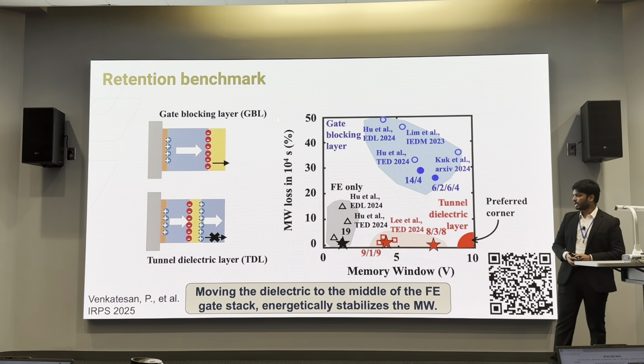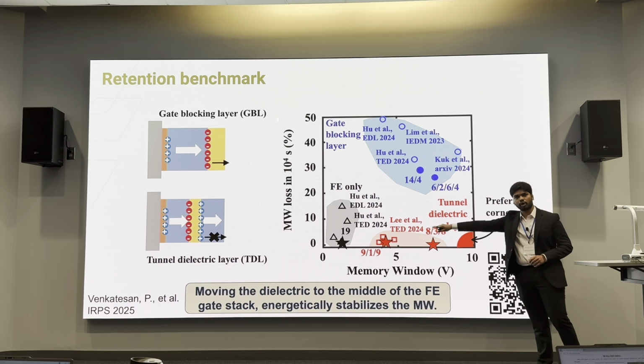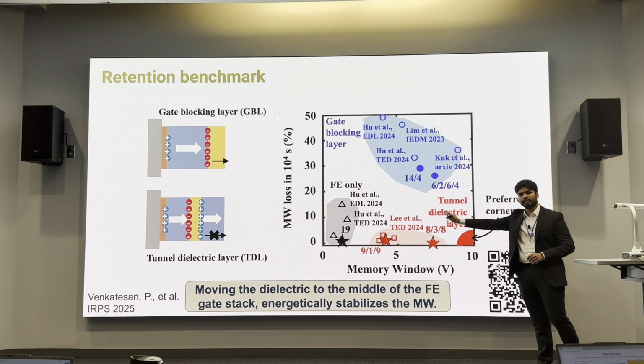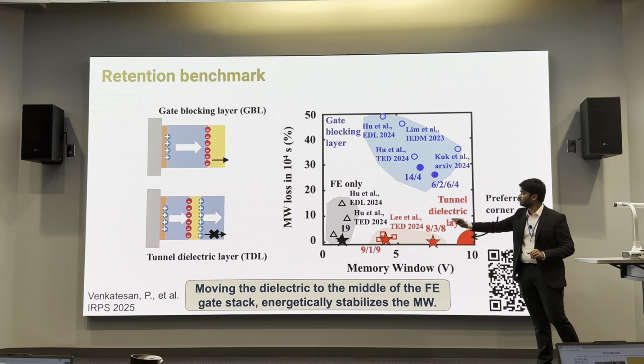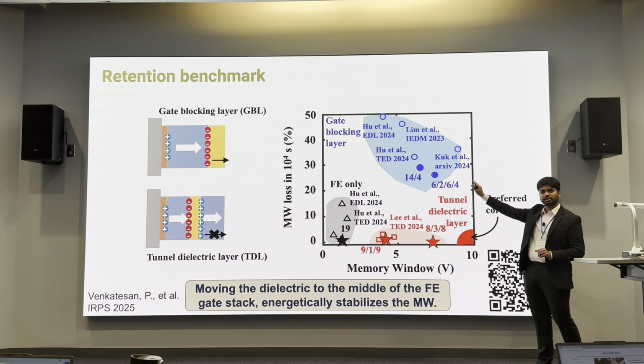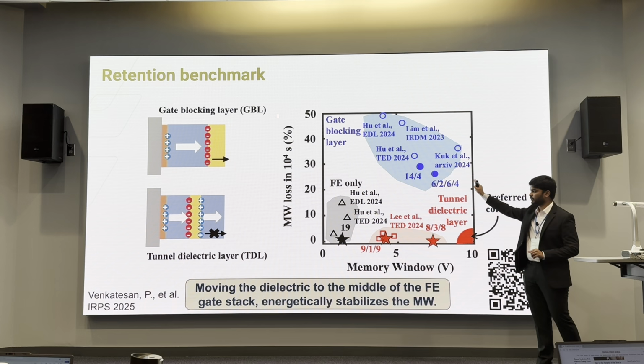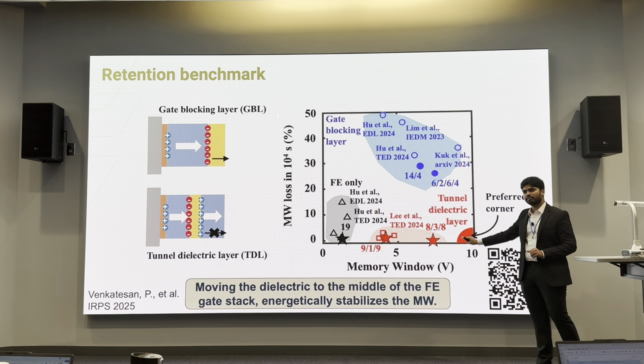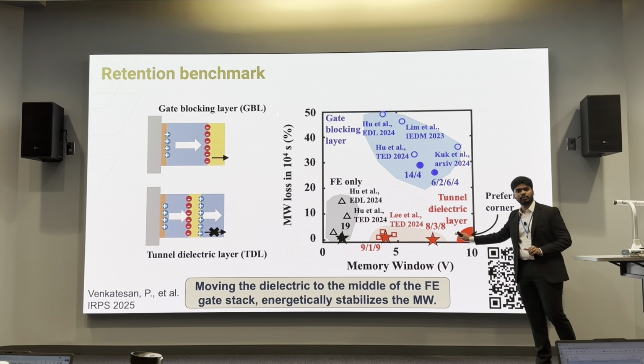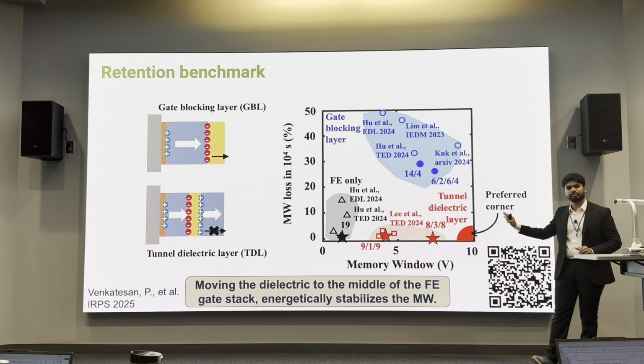So we have robust retention in our tunnel dielectric layer stacks. Again, a quick summary. We have on the left bottom the standard ferroelectric devices, which have lower memory window but decent retention. Then we have the gate blocking layer devices, which have large memory window but huge retention loss. And then we have our hero devices, which are the tunnel dielectric layer devices, which have a large memory window and at the same time robust retention.